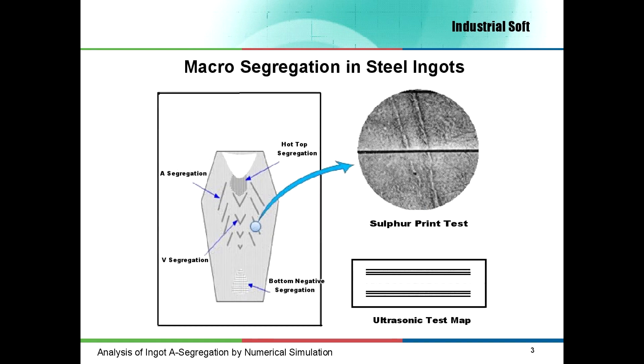The analysis and the technique I will present refers to A-segregation, one of the types of macro-segregation. We can find this kind of material heterogeneity in the zone of transition from columnar grains to large equiaxed grains. This segregation presents channels enriched by carbon, phosphorus and sulfur, and can be put in evidence by sulfur print test. It has as result both defects detected by ultrasonic test and heterogeneity of material and mechanical properties.